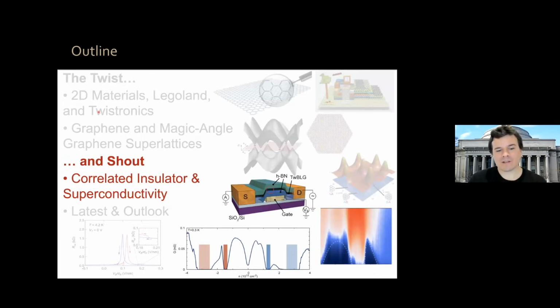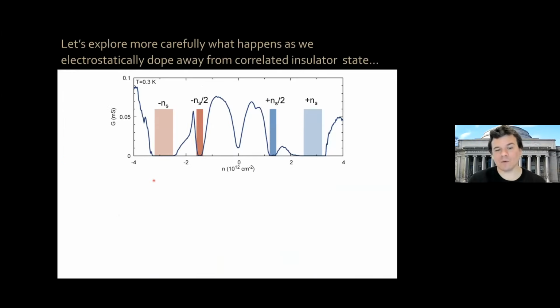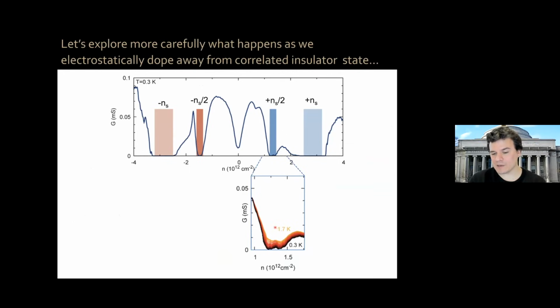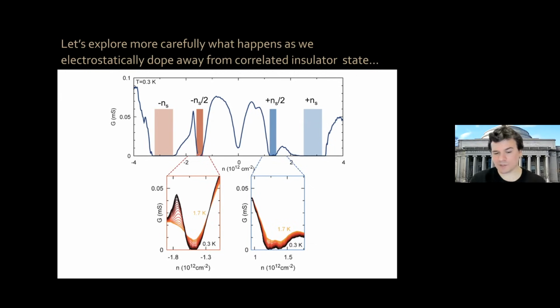Now, let me tell you more, okay? When we were measuring these devices, we were looking at the correlated insulator state behavior here, okay? We were doing temperature dependence. These are all low temperature data. And we saw that as we cool down from 1.7 Kelvin to 0.3 Kelvin, the system conducts less. And that's what you expect from an insulator. The colder it gets, the lower the conductance, okay? If you look around the correlated insulators for electrons, same thing happens here. The colder it gets, the less it conducts. However, if we just add a few extra holes to the system, it seems like the colder it gets, the better the system conducted, okay? So that conductance enhancement was kind of unusual, okay?